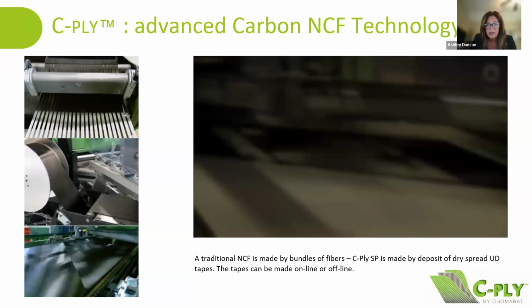So in the upper image, in the top left, you can see this is our dry spreading line. This image shows where carbon fiber tow bundles are spread into a thin, flat, unidirectional tape. And then the center image shows the completed tape, which is then transferred to the multi-axial line, or MAX 5, where the tapes are positioned into precise orientations. This could be plus or minus 45, 0, 90, and then also 30-degree shallow angles.